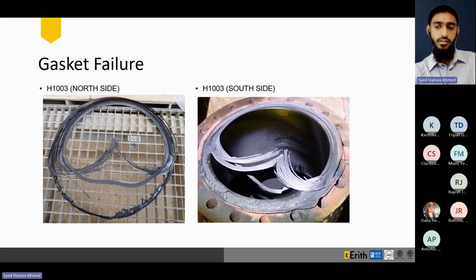The media contained in this line was hydrocarbon, and the process flow stream had a high flow rate of 175,000 kgs per hour. So this extreme amount of torque that was applied by the installation, almost double the amount of the recommended torque, crushed the gasket and caused it to buckle into the process stream, and eventually the gasket failed and the line had to be opened prematurely.